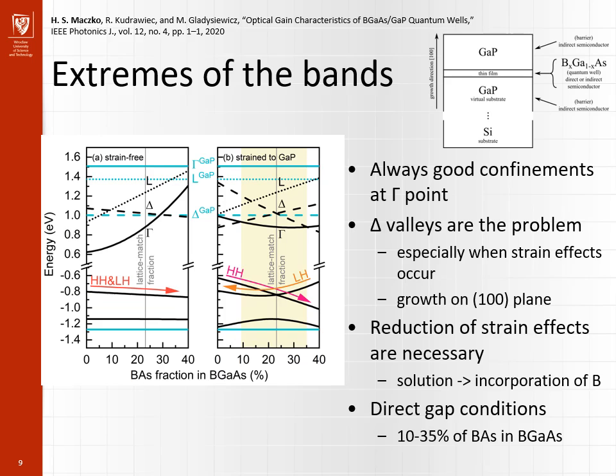However, very close above the minimums of conduction bands in gamma point there are minimums of delta valleys. These valleys are limiting the fraction range in which a thin film layer is useful for light-emitting purposes. Visible splitting of delta valleys is connected with the strain induced by substrate. Pure gallium arsenide grown on gallium phosphide would be strained so much that it would have an indirect gap. Therefore, in this system, boron atoms in the thin film are necessary for reduction of strain so that direct gap conditions can be achieved. For this reason, a fraction range from 10 to 35% of boron arsenide in boron gallium arsenide is interesting.